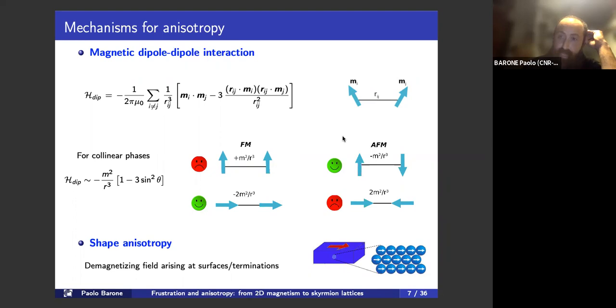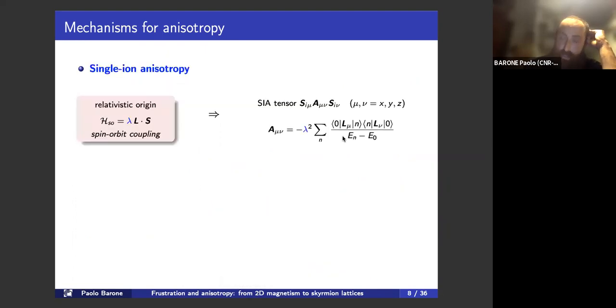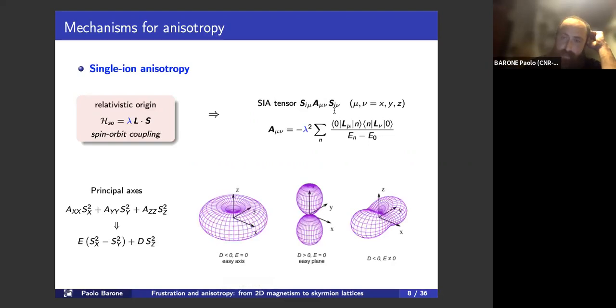A much more effective mechanism is the single ion anisotropy. This has a relativistic origin. It's a perturbative expression, it's very simple, it's shown here. And it's, of course, a tensor that comes from the fact that we have in this perturbative expansion the matrix elements of the orbital angular momentum. And typically, this can be expressed by diagonalizing the tensor in the basis of the principal axes. And this is the formulation that is most often encountered in terms of longitudinal and transverse components.